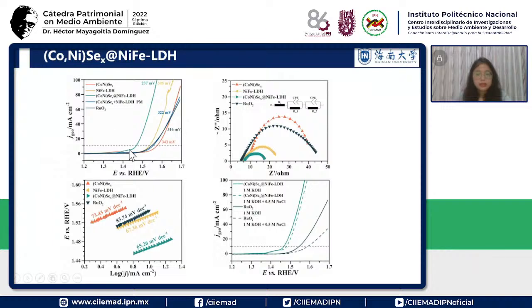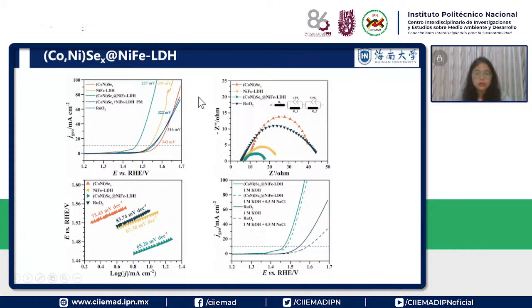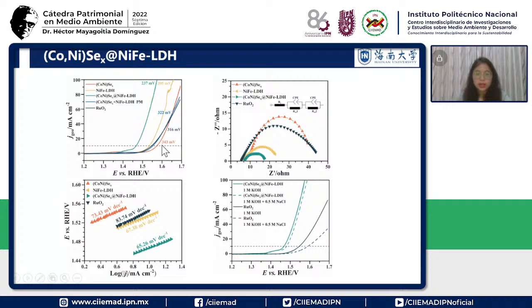Now we can see, compared to the nickel iron LDH, the orange curve, and the red one, the selenide, this composite shows much enhanced OER activity. To achieve a current density of 10, it only requires 237 millivolts, but the others are higher than 300, even 343. Also, this composite shows the smaller resistance.